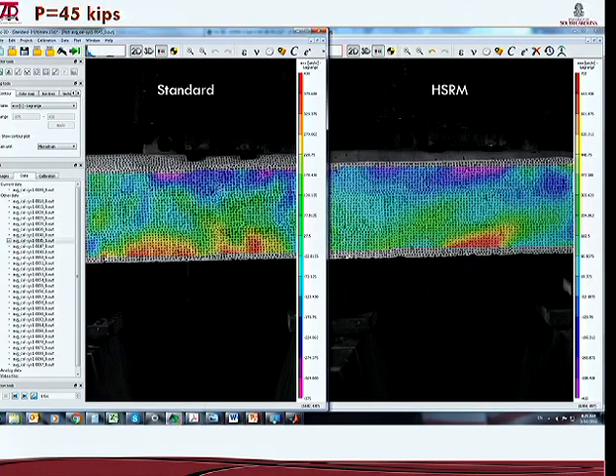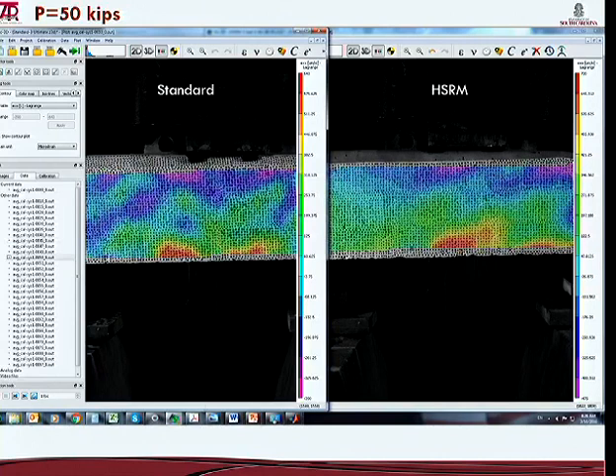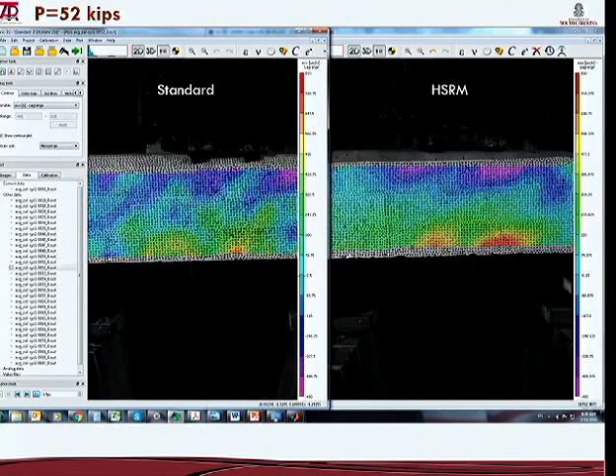Here we're at 430 microstrains, 725 microstrain. Remember, we need 1100 plus for the HSRM to crack and 700 plus for the standard to crack. So 50 kips, still below the cracking load. The strains hover about the same values. Now at 52 kips, this jumped up to 820. So there is a crack. And if you take a closer look here with extensometers and such, we were able to pick it up. HSRM has not cracked yet, but you see higher strains that are spreading out.